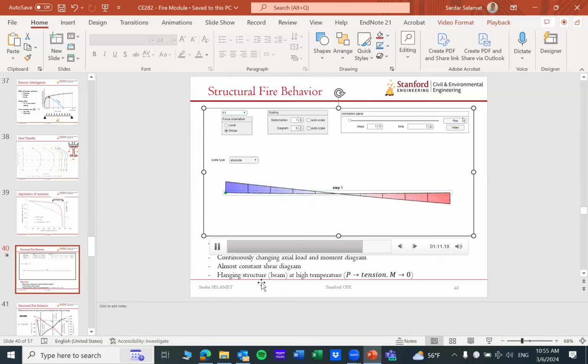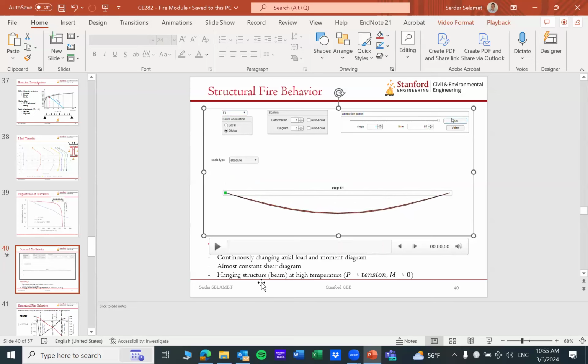The third one that he looks at is the midspan moment. Obviously, WL squared over 8 in the middle, and then you can see the moment is also reducing almost to zero. So what does that mean? The beam acts like a cable. No bending, almost no bending, and it's in small tension. And this happens during the heating phase only. It's not cooling. So the beam starts to hang from its supports, and that makes the support conditions very, very important.